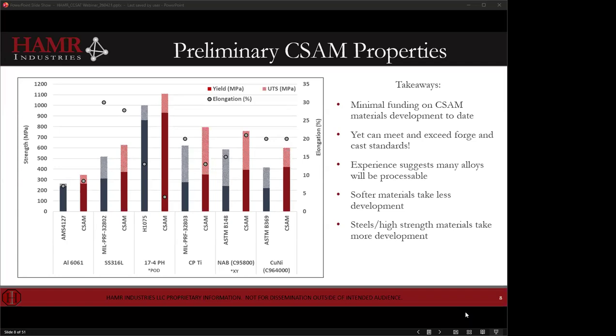So you'll see 6061 on the left. Cold spray additive can meet and exceed AMS 4127. So we are able to meet and exceed forging level properties of 6061 with cold spray additive. Likewise, on the maritime side, NAB and copper nickel, there's going to be a lot more information that'll be public by the time of CSAT that Penn State's going to present on. But for what's been done privately, there's already evidence of meeting and exceeding the NAB and the copper nickel ASTM standards in cold spray additive.